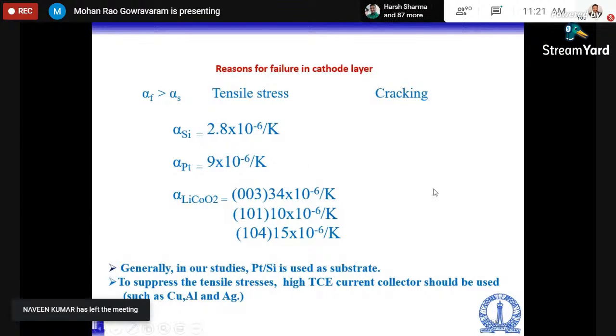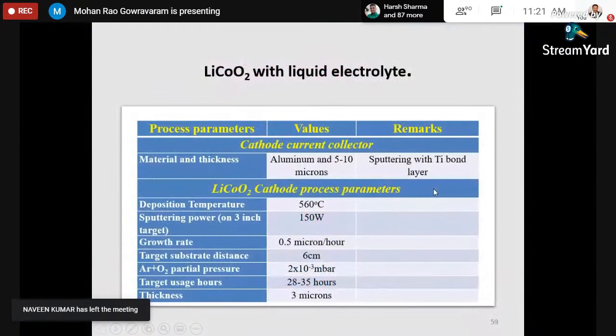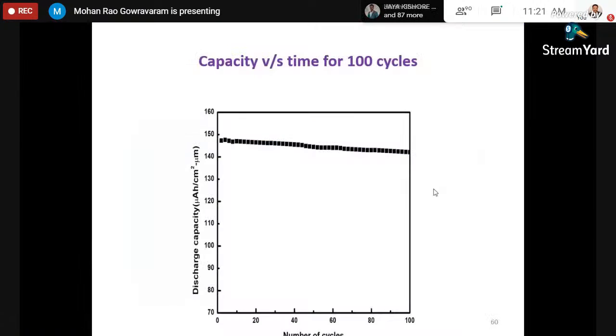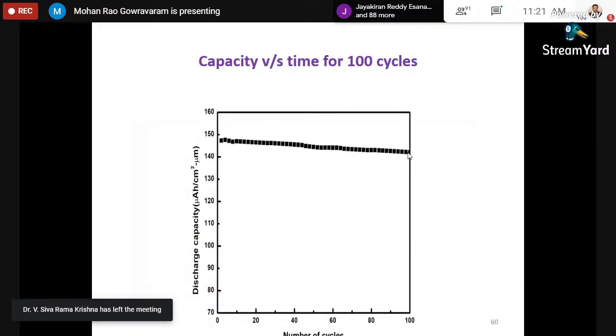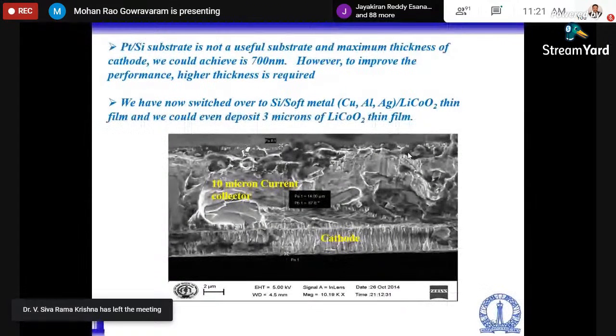So with that aluminum, you deposit this and then you optimize the parameters, and you have, even after 100 cycles, the discharge capacity has not fallen, and so it is a very good modification to the process that we have done.